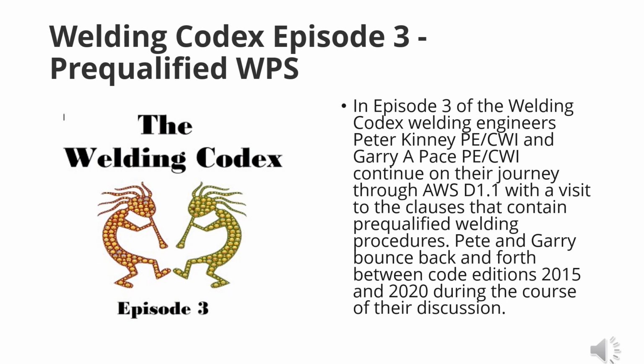All right. So to come at it from a different direction, then maybe put some context into what Pete was saying: Group One is the shallow end of the pool. You really got to work to mess this material up if you're welding it. And I say that, I'm probably going to get hate mail again, but for the most part, you can get some 7018 or 6010, and if you are relatively competent at welding, you should be able to weld this material and not have too much difficulty.